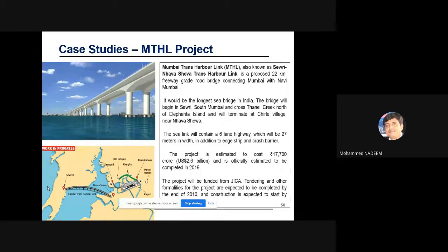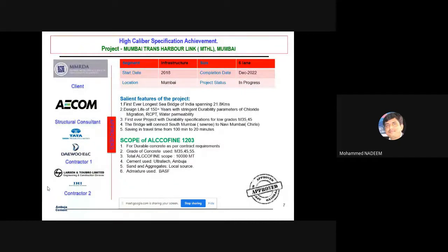They did a lot of trials, and concrete is being made using only 190 kg of cement, 325 kg of GGBS and 50 kg of Alcofine. With this combination, they are able to get concrete satisfying those durability requirements. This project is designed for a life of 150 years. You can't think of replacing a bridge of 22 kilometers, such an important structure, within 10, 15, 20 or 50 years. Naturally, you need a longer service life, which is possible with concrete, in this project going on in Mumbai.